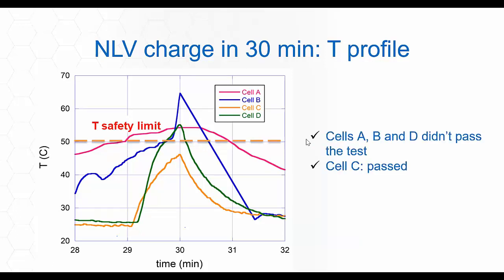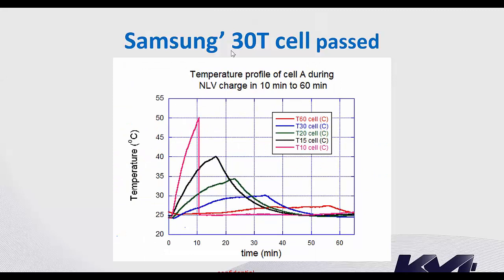And by the way, the Samsung 30T cell passed all the tests from 60 minutes to 10 minutes, okay? And you can see here that when we use 10 minutes, the temperature is 50 degrees. It's still below the limit. And when the charging time is 15 minutes, 20 minutes, 30 minutes, and 1 hour, you can see that the temperature profile is dropping. So we are below the limit of 50 degrees C. So this 30T cell can be used for many applications where fast charging is required.